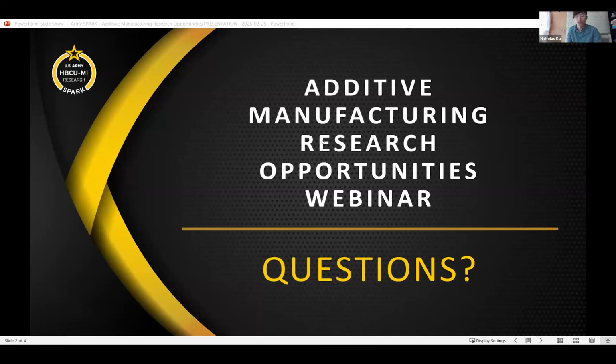Suspension development and formulation is definitely one that we spend a lot of time on, and we would perhaps like a bit more basic fundamental knowledge to reduce the size of the test matrix that we usually start with, or to get a better polymer off the bat. One thing I would also say is that any binder we put in, we do need to burn back out. Understanding debinding, in terms of polymer pyrolysis and how the gases escape from these powder networks, is also definitely an area of interest.